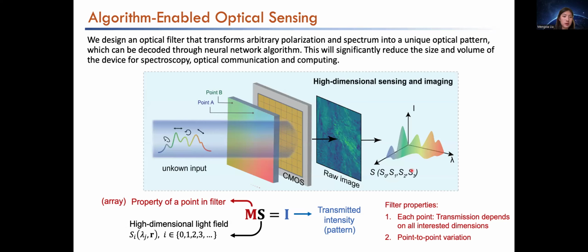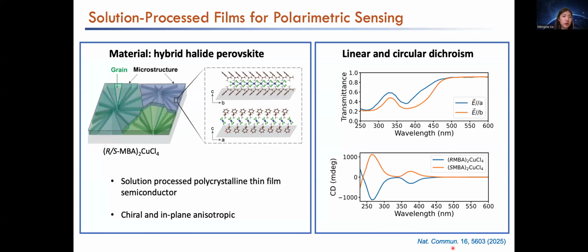And we try to develop some materials that can create this required property for the filter. What is important is that on each point, we need the transmission to depend on all of the dimensions of interest, for example, polarization and spectrum. And also we need to have a point-to-point variation. The first material we look at is, again, halide perovskite. But this halide perovskite has a very strong anisotropy, which means if you look at the material along the b-axis versus along the a-axis, the material looks very different.